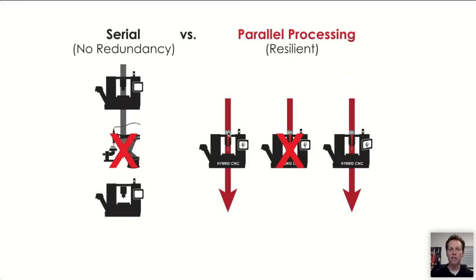And in fact, in the case of GE, the machine that went down was doing additive, subtractive, and inspection. They crashed the additive head. So they were still able to do subtraction and inspection. So what they ended up doing is repurposing this machine that was down for about a week and a half, only to do subtractive and inspection. So in that way, they actually got more than 2/3 throughput, or were potentially more than 2/3 of their throughput through. So this resiliency, avoiding the interdependence of serial, is another powerful thing for consideration.